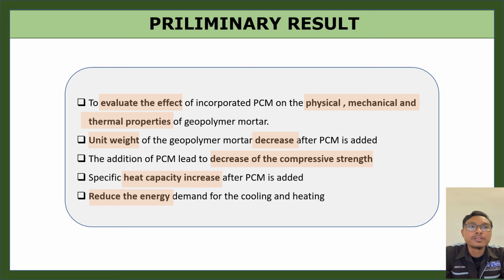The unit weight of the geopolymer mortar decreases after PCM is added. The addition of PCM can lead to a decrease of the compressive strength. Specific heat capacity increases after PCM is added. The thermal test with a cubicle further proves that the geopolymer mortar incorporated with PCM can be used as a building wall to effectively increase the thermal inertia of the building and reduce the energy demand of cooling and heating.